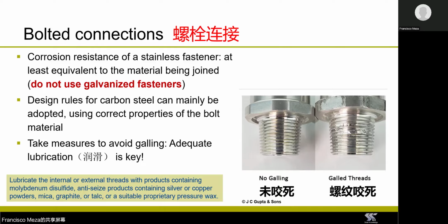Now, there are measures to minimize the risk of galling. And a very important measure is to select an adequate lubricant. So you should make sure that all the parts that are going to be in contact and in relative motion with each other are properly lubricated. There are other measures that you should take, and this includes reducing the tightening speed and also ensuring that the threads are free from grit or abrasive materials.